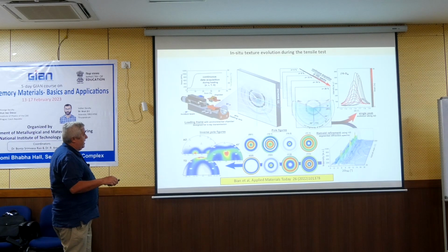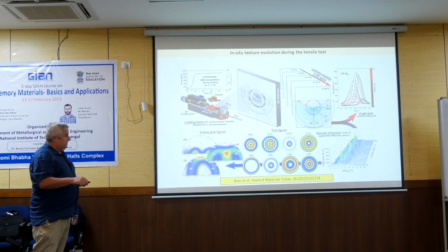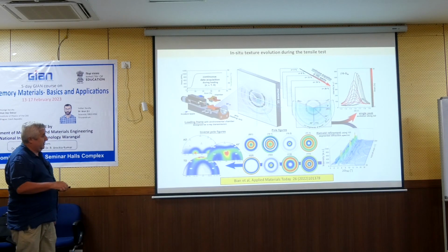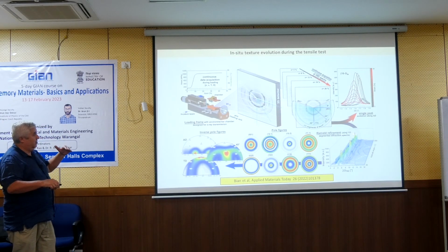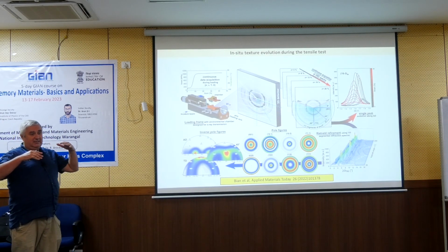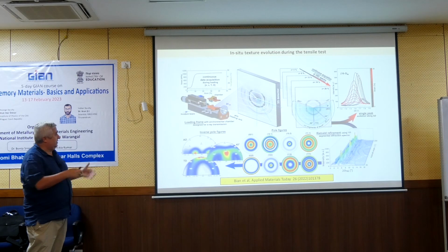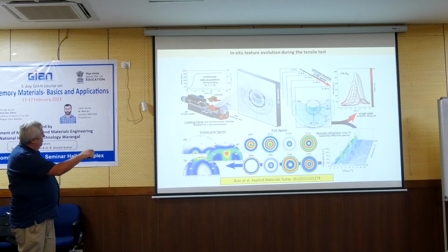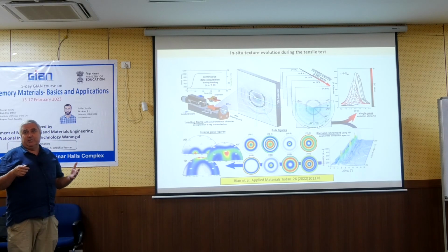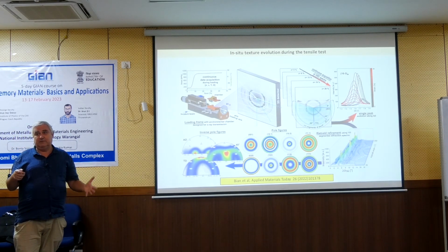The experimental procedure is a little difficult, but very reliable, and it took us some time to master all this process. For example, the simultaneous Rietveld refinement on 111 spectra took us really a long time, one day. So it was impossible, because along the stress strain curve you can have 2,000 points, and if one analysis takes one day, it will not be possible.